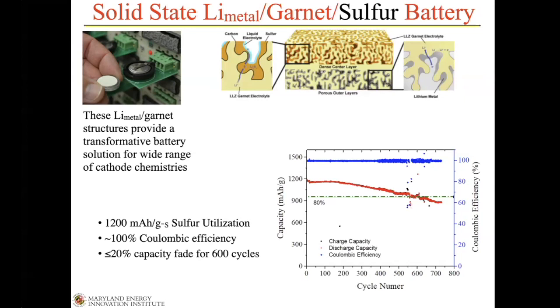A lot of people worked on lithium sulfur batteries. They have a problem, what's called a polysulfide shuttle, where the sulfides form on the cathode side and diffuse through the liquid to the anode side. Again, because of that dense ceramic electrolyte, we block that polysulfide shuttle. And so theoretically, we should have very, very high stability with these types of cells. And this is some of the initial data to show that.